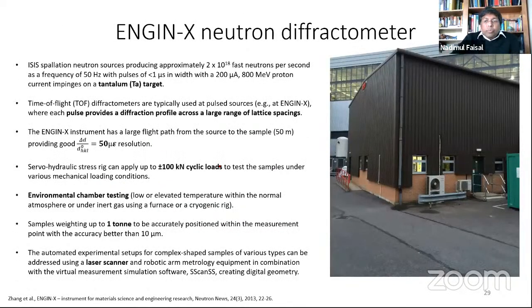Now, a few details about the source itself. This one is based on a tantalum target. It is based on time of flight. The resolution is 50 microstrain. If you have samples less than 50 micron, I'm afraid this will be a challenging one. You can also apply fatigue loading on your samples. You can deploy different temperatures, cryogenic temperature, or a furnace. You can have large samples, you can have small samples, or you can also do some scanning of the sample if you pinpoint which coordinate or location of the sample you want to analyze. So these facilities can be accessed.